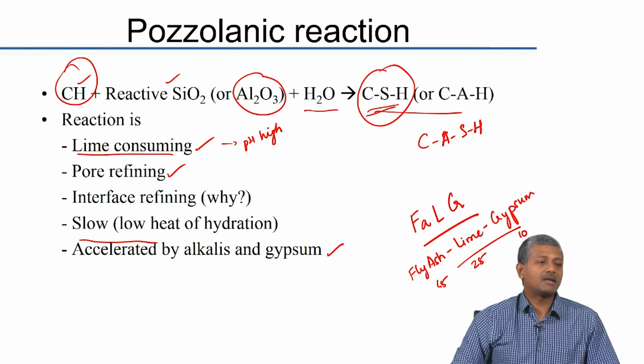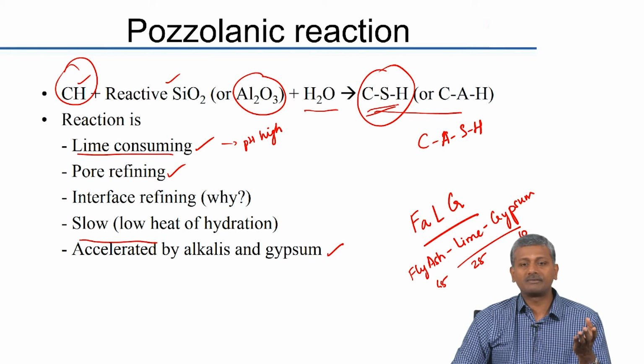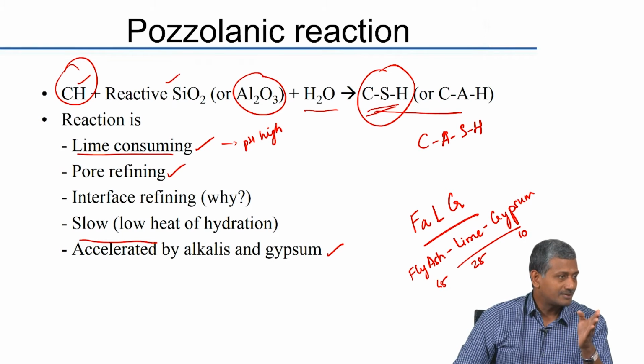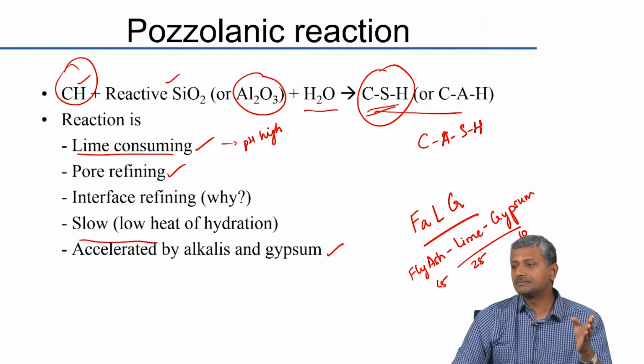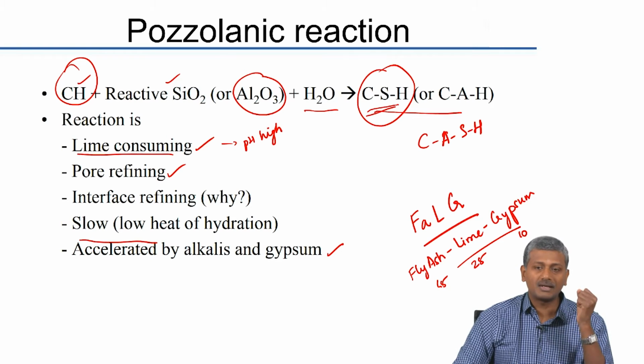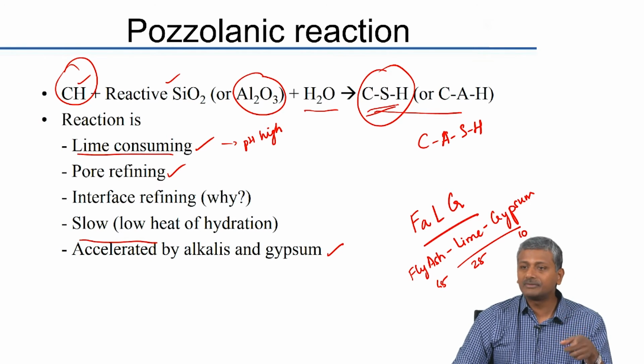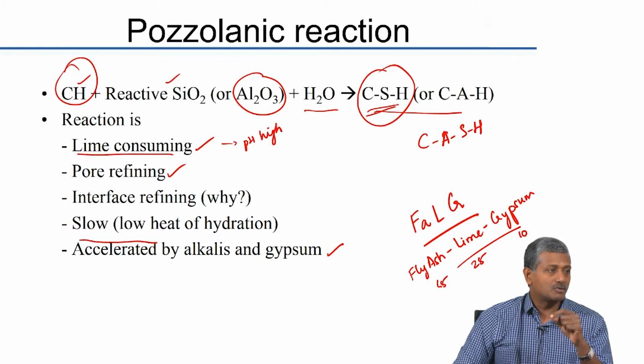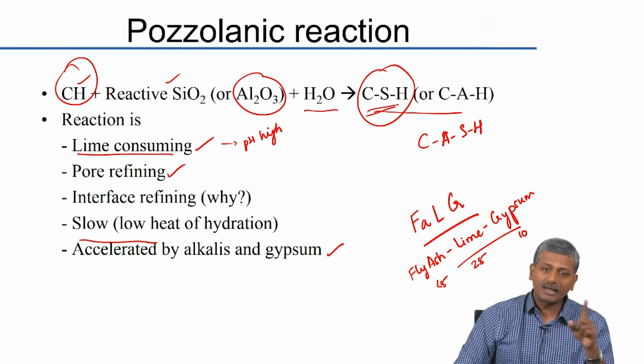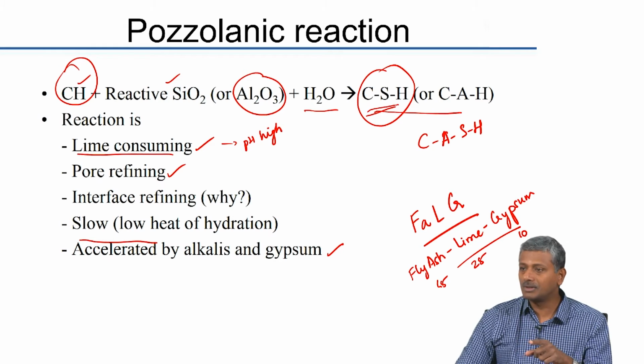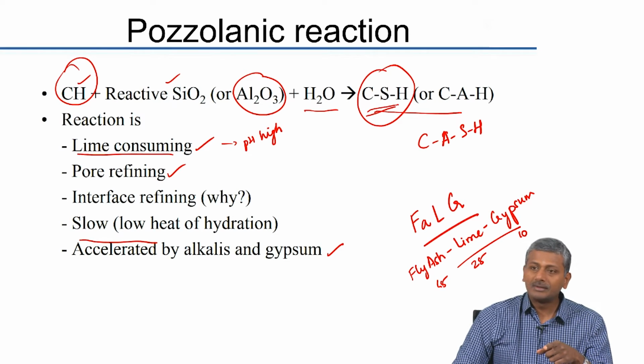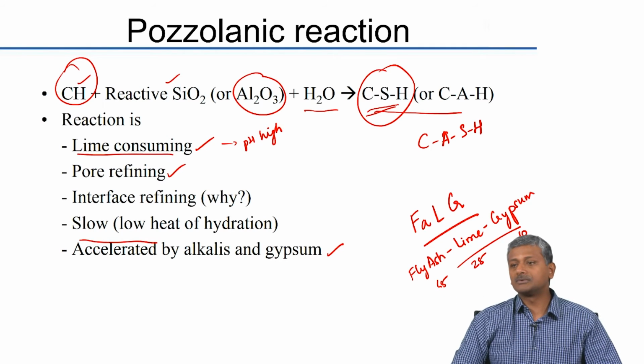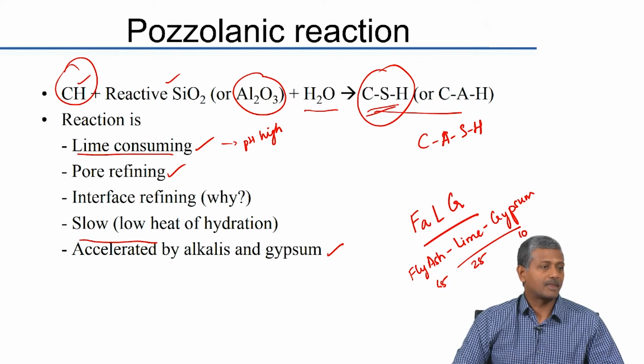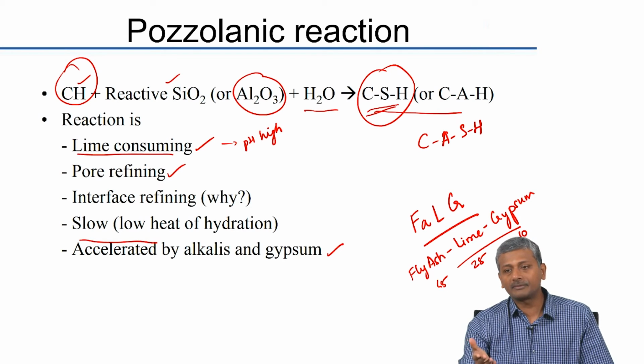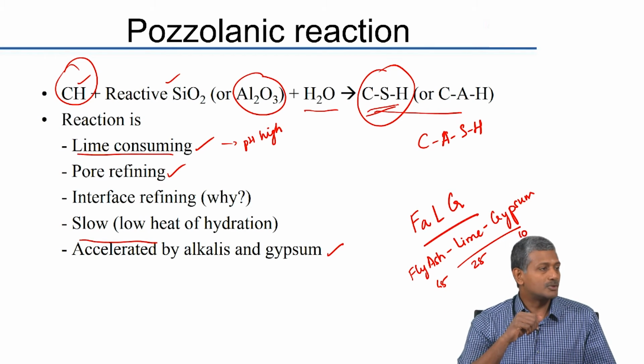Now, what happens in the case of mineral admixture mixes is that since you do not have sufficient calcium hydroxide available, the carbon dioxide can now directly attack the other calcium bearing products like CSH. Your CSH starts getting attacked directly, and when that happens, you have a possibility of a more porous network forming in the system, okay. Whereas the attack on CH leads to formation of more dense concrete, attack on calcium silicate hydrate may actually create a slightly more porous network in your system, which further propagates the carbon dioxide into the concrete system. So, when you substitute cement with mineral additives, you will definitely get greater propagation of CO2.